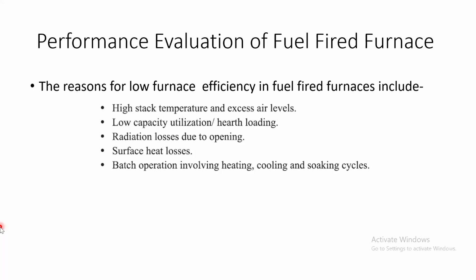So ultimately that wait time can be 8 hours, 10 hours, and that will reduce the efficiency of the furnace because of the batch operation. When the furnace gets cooled from a high temperature, sudden thermal stresses occur, because it goes from a melting temperature of say 1500 degrees to atmospheric temperature all of a sudden. Due to such a huge delta T, there is a thermal stress in the furnace, and that results in lower efficiency.